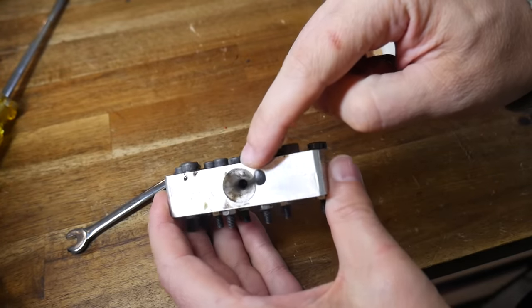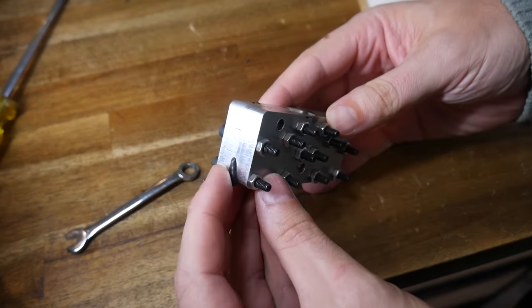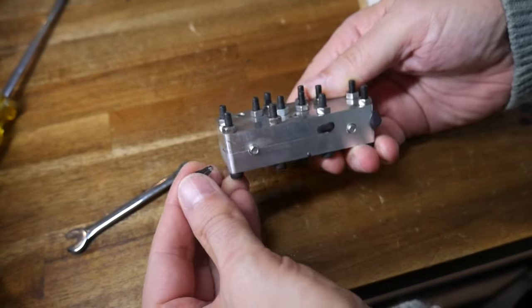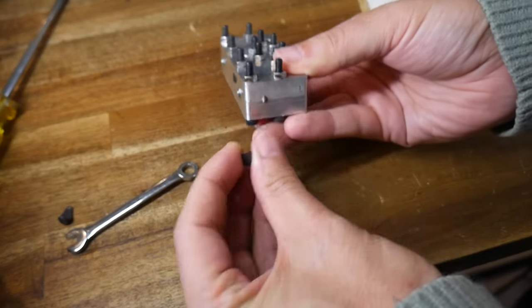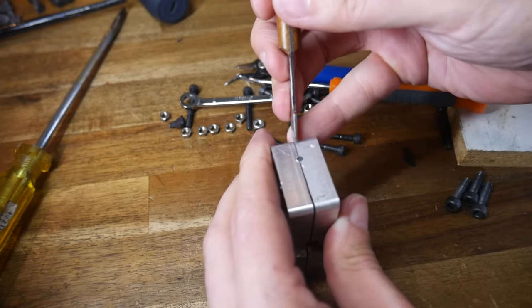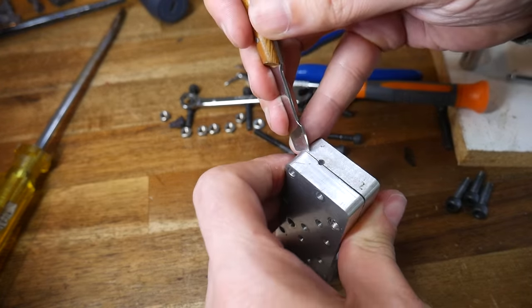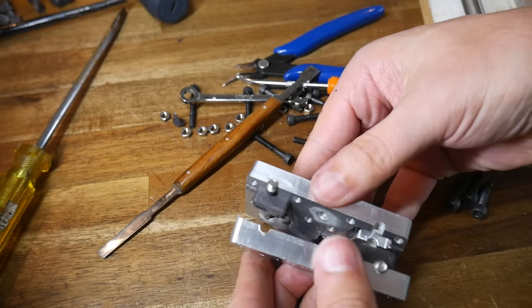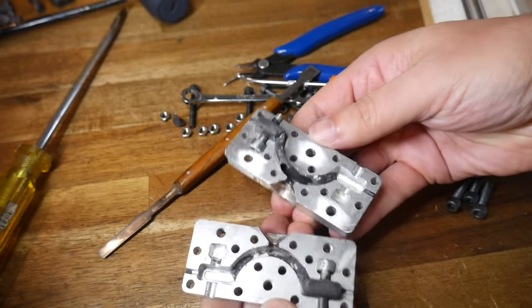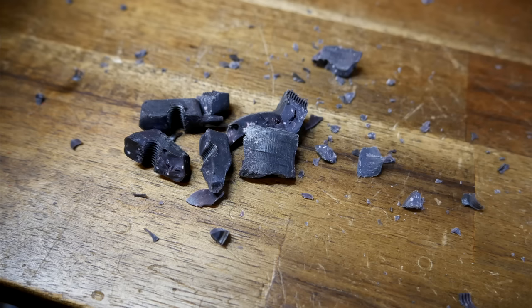This time, I avoided the freezer and forced myself to be patient. Concerningly, there was a bit of shrinkage in the entry hole, but apart from that, everything looked legit. But the second time, the mold needed some persuasion to separate back into two halves and despite my changes, I was horrified to find that my molded piece inside had disintegrated once more, which was only exacerbated by the rest of the removal process.